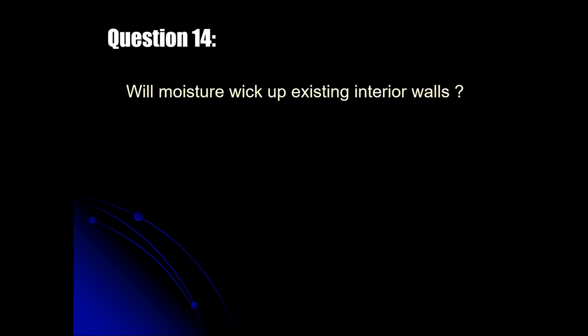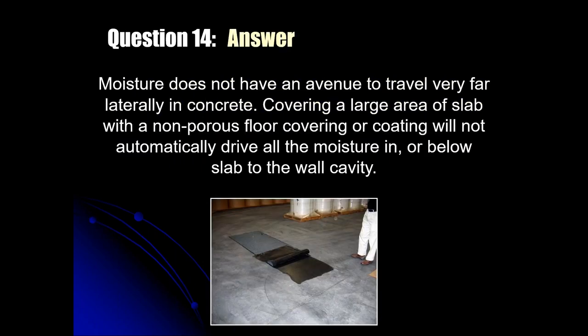Will moisture wick up existing interior walls? Well, we've learned that moisture really doesn't have an avenue of passage laterally in concrete to any significant measure. If you think about it, if it did, when we put down a floor covering over a room, all the moisture would go, be like a chimney effect right to the wall cavity, and that simply is